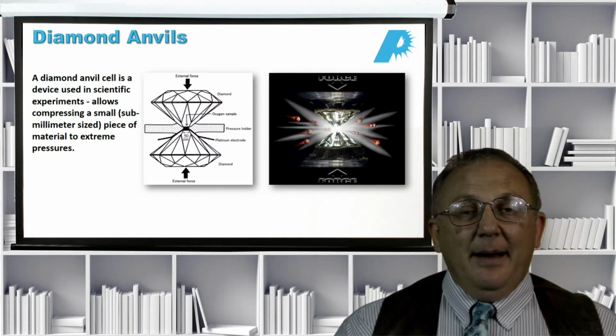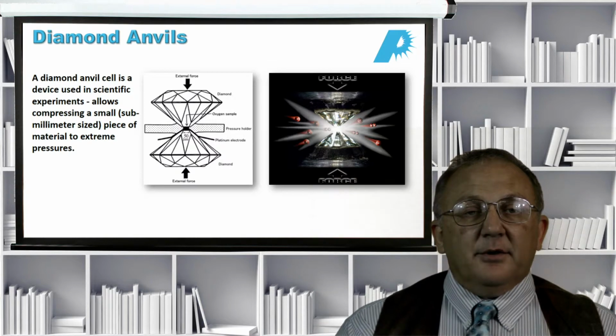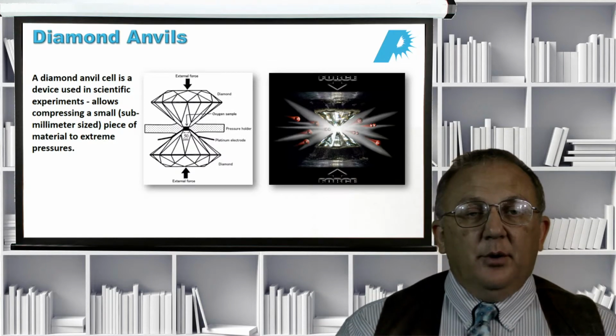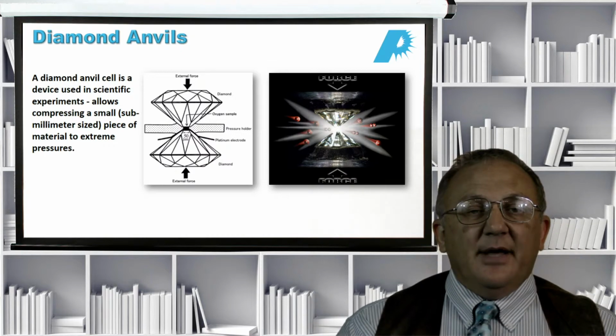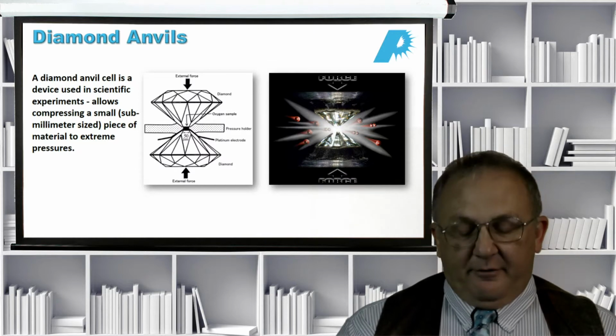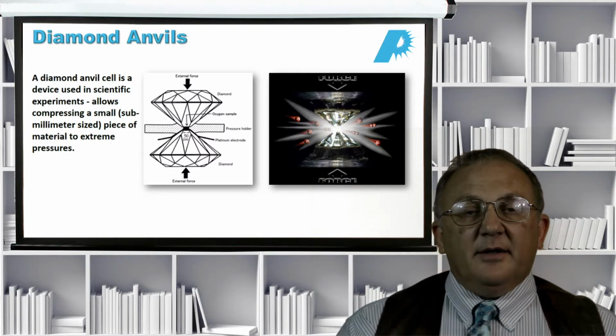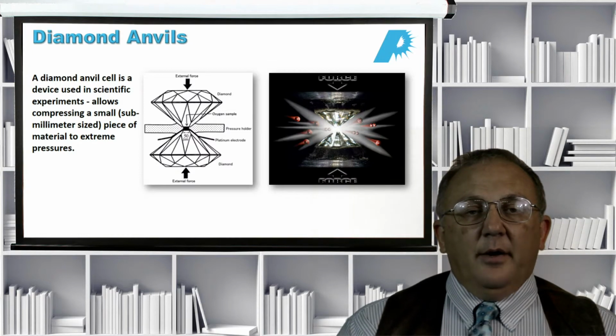Another application for diamond drilling is the making of diamond anvils. Diamond anvils are used in scientific experiments to generate conditions that are sort of like in the interior of stars. Very high pressure, very high temperature. And the only way that this can be done is by using diamond anvils and putting a lot of pressure on the sample chamber that's laser drilled into the end of the diamond using primarily UV lasers.